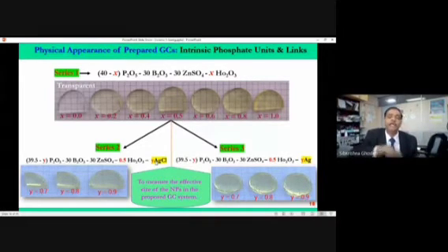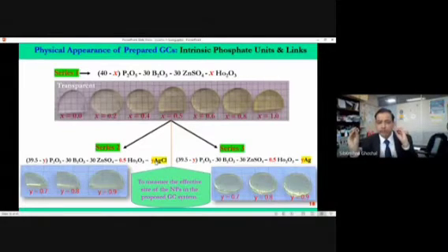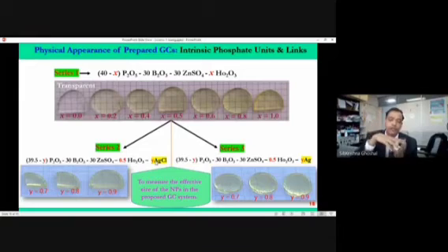If we put in silver chloride and heat it in the material, then through a process called coalescence and ripening, it will form the nanoparticle. But if we buy high quality silver nanoparticle from Sigma Aldrich or from the company Merck, we can also dope that. Then we can heat it up so that some of the bigger nanoparticles would be decomposed into smaller ones. So we started with both. On one hand, we let the system form the nanoparticle. On the other hand, we buy the nanoparticle and forcefully dope it in the system. We wanted to see which produces the better effect. That's the 3 series of glasses.